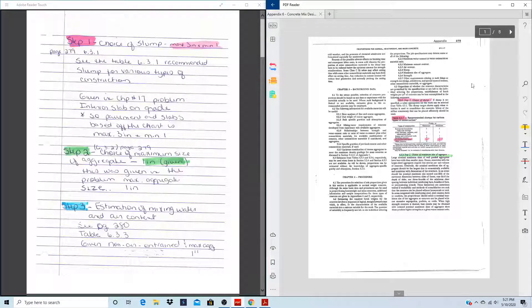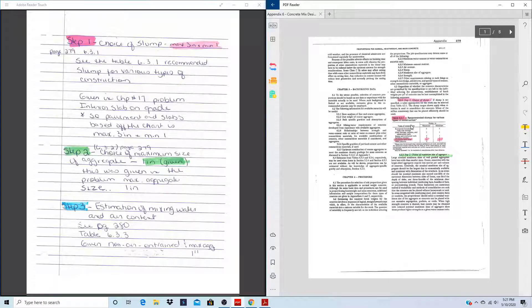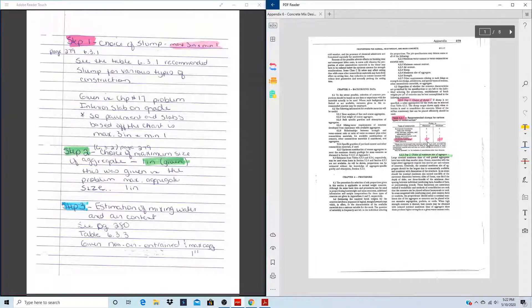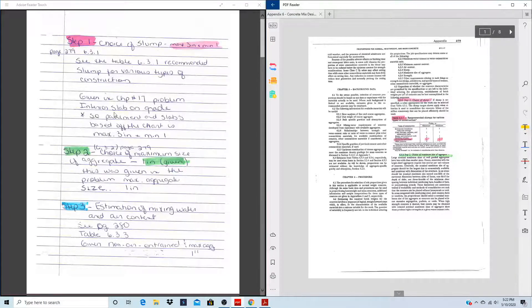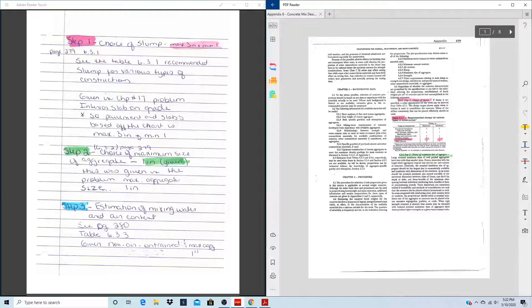Step 1 is the choice of slump. You'll use Table 6.3.1 to get your minimum and maximum slump. Our problem was a slab on grade, so pavement and slabs are 3 inches to 1 inch. Just look at what you're given — if it's footings, a wall, or a slab on grade — and that table will determine your maximum slump. Because ours was an interior slab on grade, it was 3 in to 1 in.